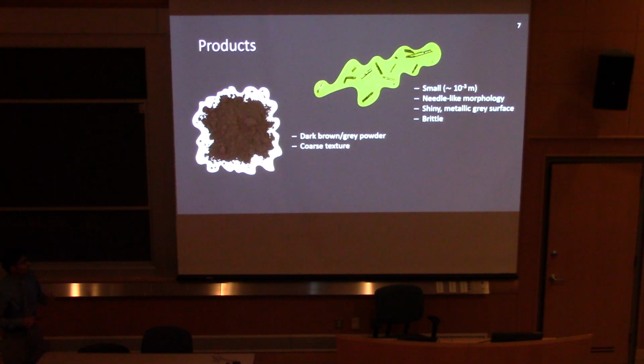In our products, the powder form is actually dark brownish gray, with a coarse texture. And the single crystal form is very small, about the millimeter scale, with a needle-like morphology and a shiny metallic gray surface. It's also very brittle, so when we try to do any measurements, it actually breaks very easily, which makes it rather painful for us.